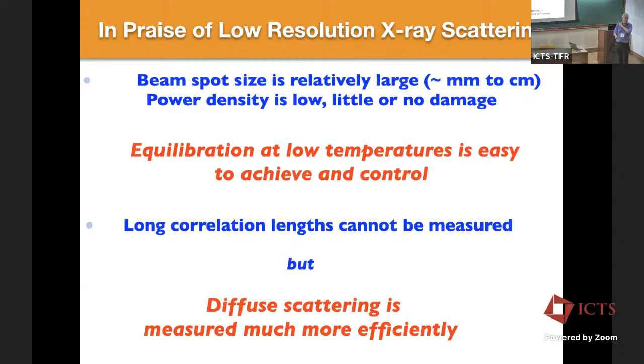So for all the measurements that I'm showing you, when I'm not listing the fluctuations in the temperature with the data, when it says 10 Kelvin, that's 10 Kelvin, plus or minus roughly 5 millikelvin or so. And the reason we've set it up that way is because when I first set up this lab some 30 years ago, what I was interested in doing was critical phenomena using X-rays and such, and so being able to control the temperature precisely was a big deal. Anyway, so we can do measurements to lower temperatures, and we can do measurements that are truly in equilibrium.